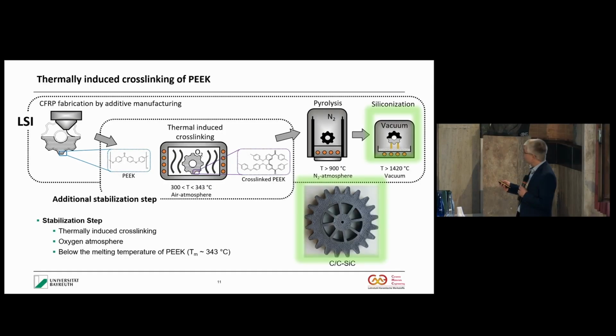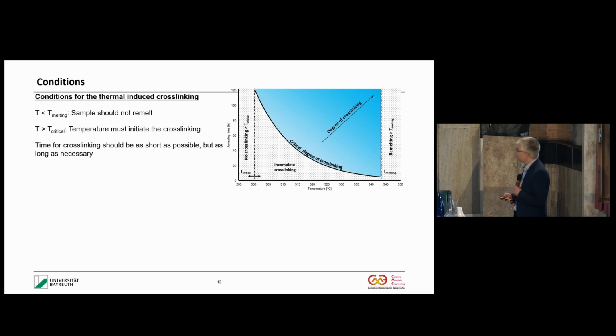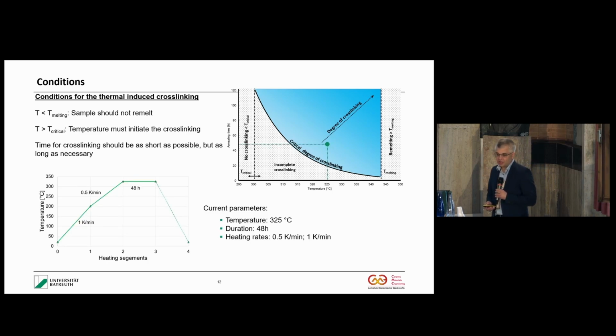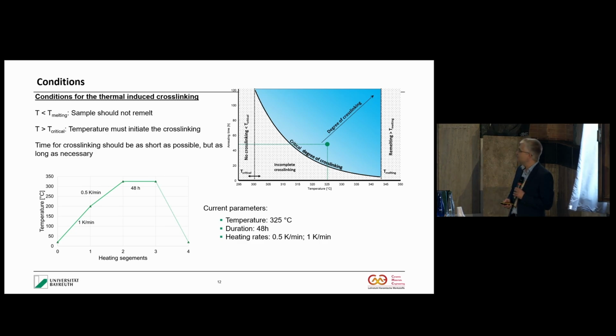And then you have this kind of cross-linking here, so it's a thermally oxidative induced cross-linking. This step is crucial in order to have the form stability during pyrolysis and later during siliconization. It's a kinetic process, so temperature is very important and time also becomes important, especially if you have larger shapes. For smaller shapes, it's relatively easy, but if you have larger shapes, you have to understand your cross-linking quite well.